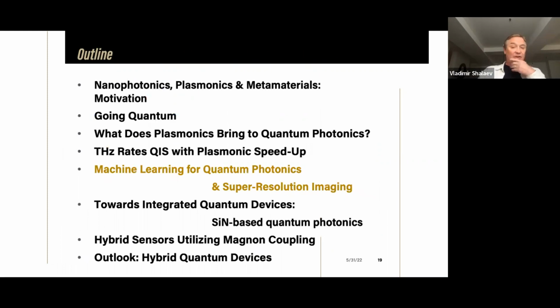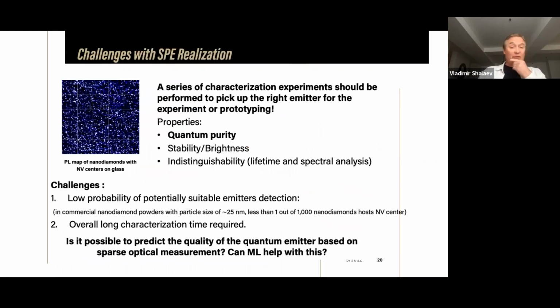Okay, so I mentioned that machine learning is very important, so let me explain why and how it could really make a difference. In the course of identifying really good emitters, that's how a photoluminescence map looks. You could see there are thousands of these nanodiamonds, and we would like them to be small, because the smaller the size of the nanodiamond, the smaller the gap between the cube and the silver film, and the stronger the Purcell enhancement. And if you, let's say, have a nanodiamond of 25 nanometers, only 1 out of 1,000 of them would host NV centers. So you really have to find a good emitter.